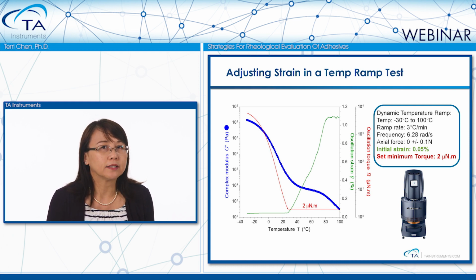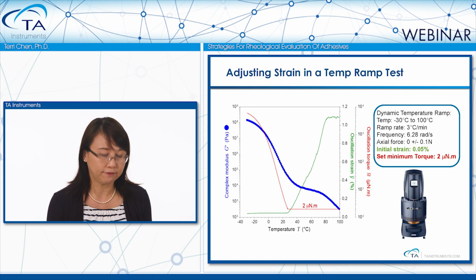The torque to control a 0.05% strain was reduced significantly. When the torque hit this lower torque limit, which in this case we set at 2 micronewton-meter, the instrument automatically switched to use a torque control for the measurement. From this particular point up to higher temperatures, the measurement torque was fixed at 2 micronewton-meter. So strain, in this case, will continuously increase as the sample gets softer. But this strain will still be within the linear viscoelastic region. This method allows automatic strain adjustment and gives very good measurement results for all temperature ramp experiments for adhesives.